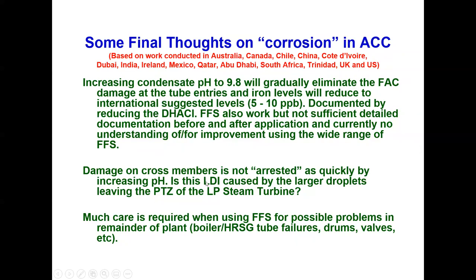Damage on the cross members and the support members doesn't seem to be arrested as quickly by increasing the pH, and there's been some discussion that this damage is slightly different than at the tube entries and could be due to what's called liquid droplet impingement because of the larger droplets that come off the back end of the turbine.